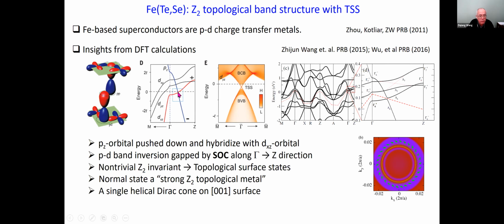So this causes a band inversion of odd parity pz and dxz band, and the SOC, spin-orbit coupling, will then create a gap along the gamma-Z direction. And this non-trivial Z2 invariant is the origin for generating topological surface states. But of course, this thing is doped. It's not exactly an insulator. So the normal state can be thought of as a strong Z2 topological metal. And there is a single Dirac cone on the 001 Fermi surface.